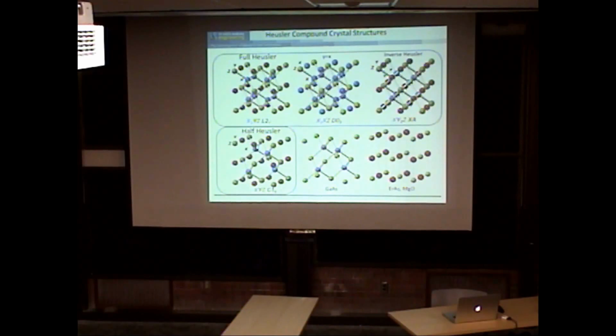Another material system is what we call the half-Heusler, where every other one of these blue atoms is missing. If you look at this material system, it really looks like zinc blende, which is a compound semiconductor, with these red atoms shoved in the octahedral sites. So the question is, when I look at these materials, do I think of them as metallic bonding? Do they look more like sp3, like you have in this compound semiconductor? And we'll talk about that, because that's where some of our properties come from.